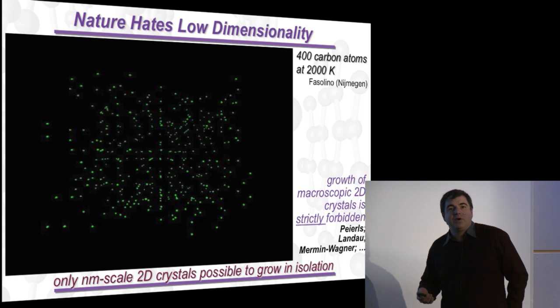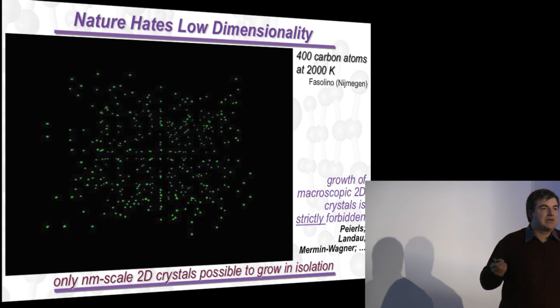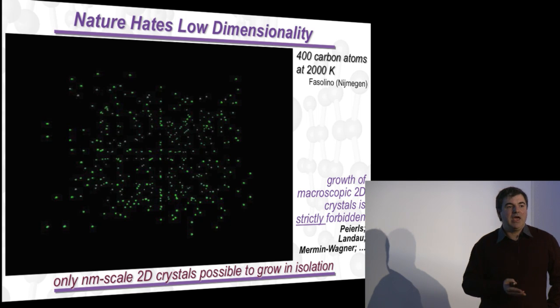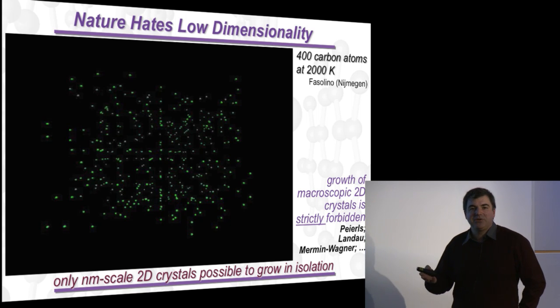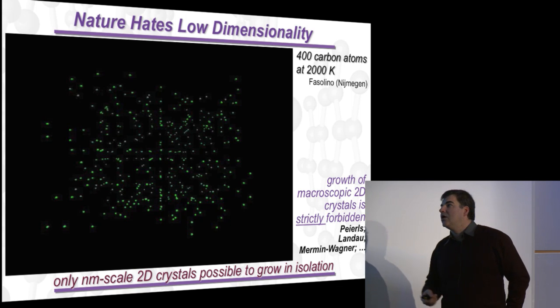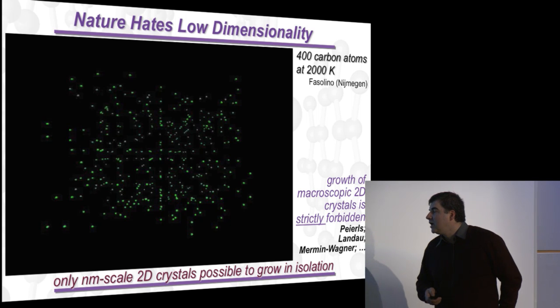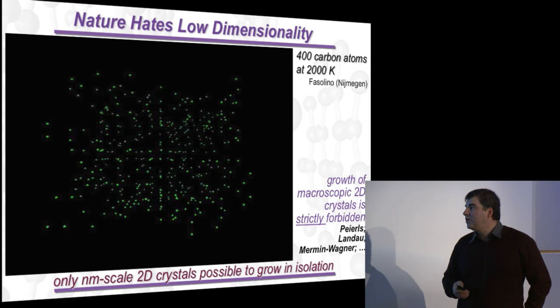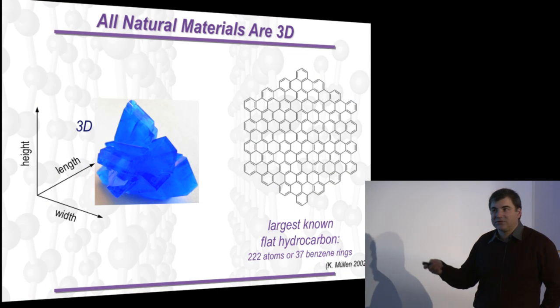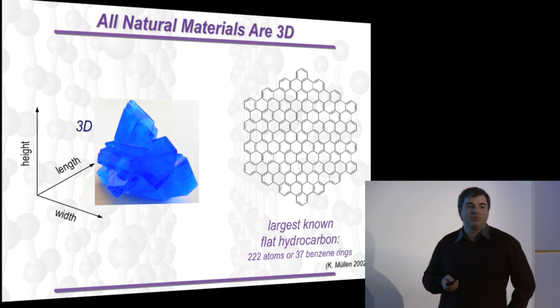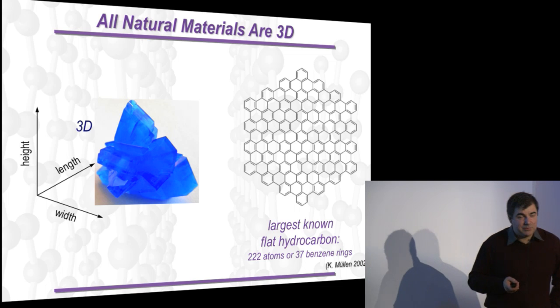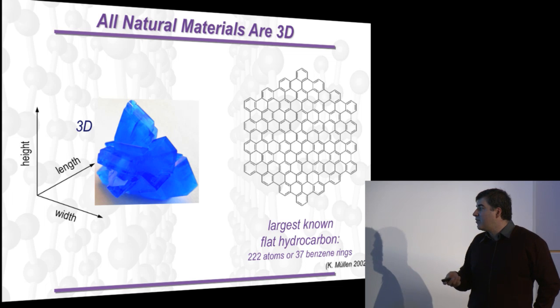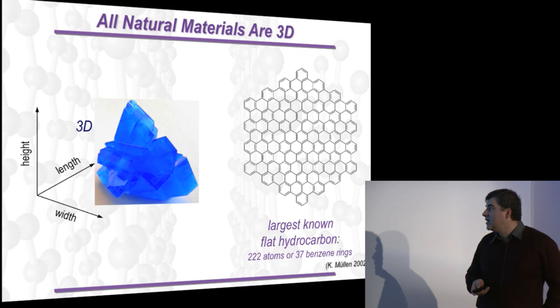So how can we overcome this problem? The critical problem here is the temperature, because usually when we grow any crystals, we use elevated temperatures, and if you try to do it with two-dimensional crystals, they will always roll up or maybe even decompose. So how can we overcome this problem, that all the crystals around us, or all the objects around us, are actually three-dimensional? That's probably the largest two-dimensional object which was available to us prior to graphene, 222 carbon atoms.